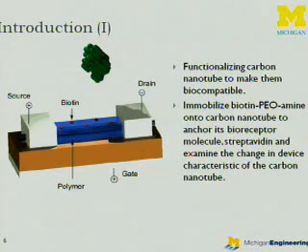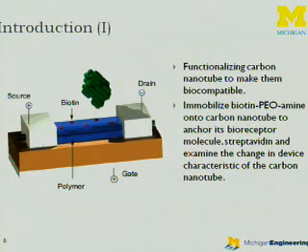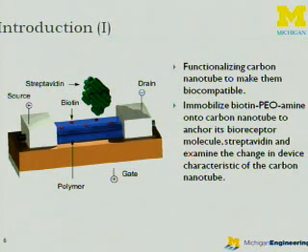Now, I will give a short introduction to my research. Basically, during this summer, I'm dealing with functionalizing carbon nanotubes to make them biocompatible. We do it by immobilizing biotin, one of the biomolecules, onto the carbon nanotube, as you can see from the figure beside, to anchor its bioreceptor molecule, which is streptavidin. For your information, biotin and streptavidin naturally bind together, and then we examine the change in device characteristics